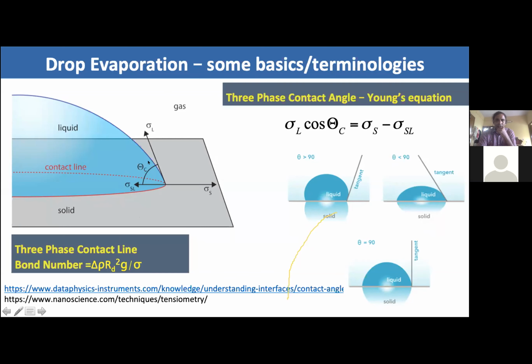One could draw a tangent to the drop surface at the three-phase contact line to obtain a parameter called the three-phase contact angle, which is related to the interfacial tension of the liquid, the interfacial tension of the solid, and the interfacial tension of the solid-liquid interface through what is called Young's equation. The contact angle theta can be different depending upon the kind of substrate. You could have a substrate where the contact angle is greater than 90, or less than 90. When the contact angle is greater than 90, you typically term these surfaces hydrophobic. When the contact angle is less than 90, you think about hydrophilic substrates. And when the contact angle is exactly 90, they are called neutrally wetting substrates.